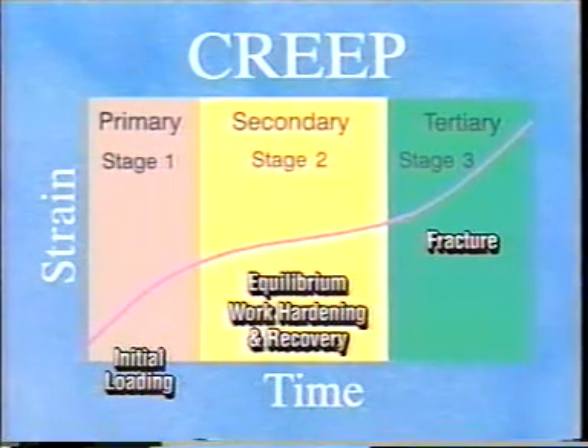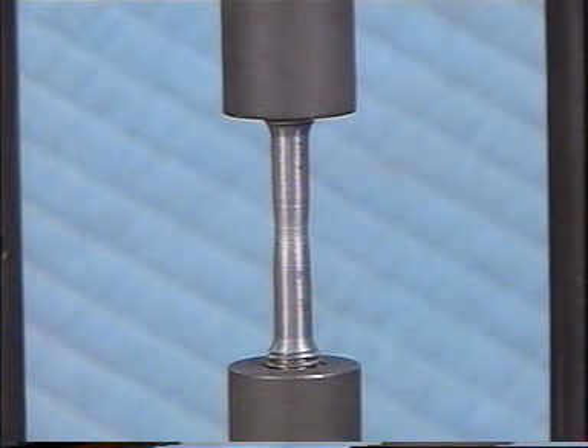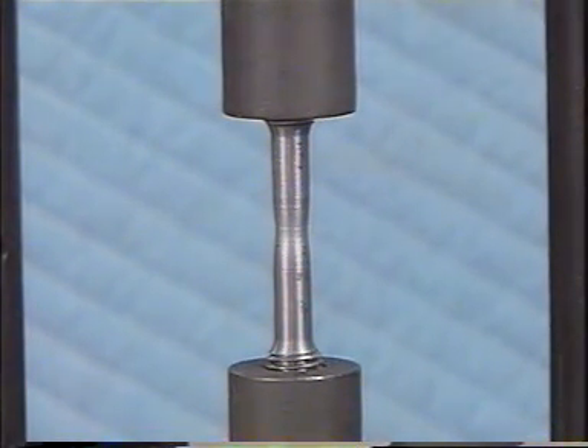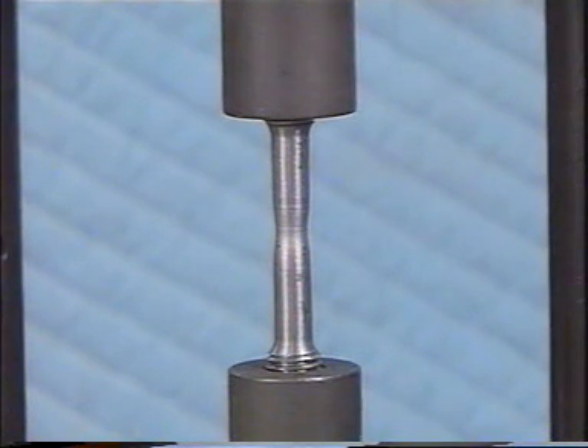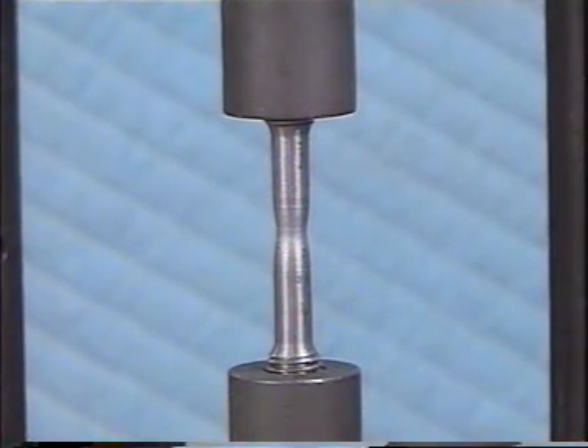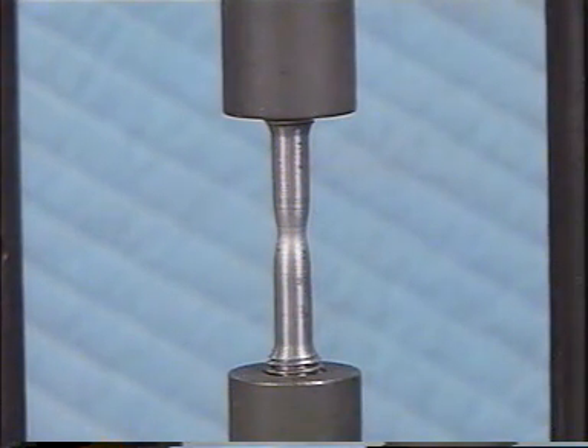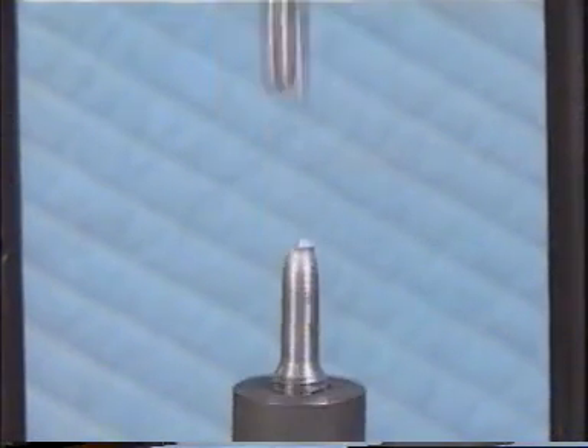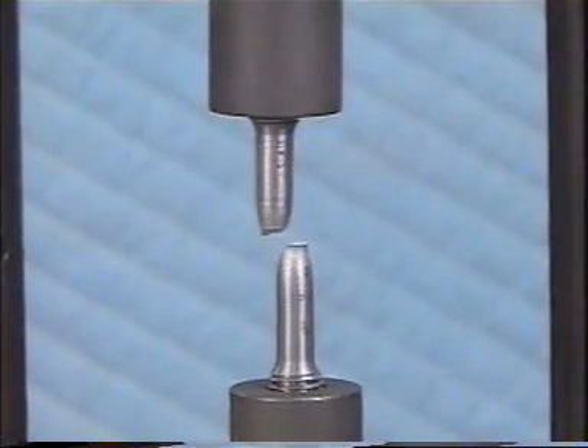Tertiary creep is the third and final stage of creep. The rate of extension increases and is followed by fracture. Tertiary creep occurs when the cross-sectional area of the metal decreases by necking or cracking, or both, and the creep rate accelerates. This creep rate will be increased by any environmental conditions that decrease the cross-sectional area. Tertiary creep may also result from metallurgical changes, such as recrystallization under load.